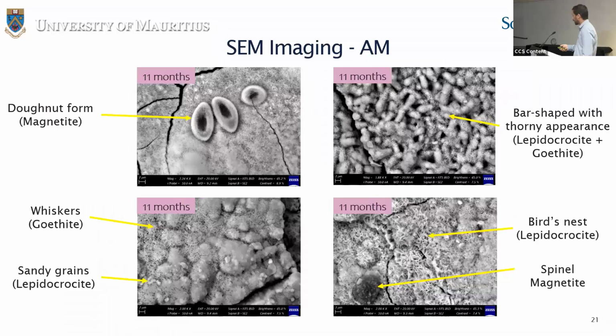Using the scanning electron microscope, the surface morphology of the corroded specimens was examined. At AM, as at other sites, there are different forms of lepidocrocite which are observed: sandy grains, bird's nest, and bar-shaped. And the bar-shaped one, with its thorny appearance, implies the presence of goethite as well. Goethite also occurs as whiskers, and magnetite was seen as spinel and in the typical donut form.